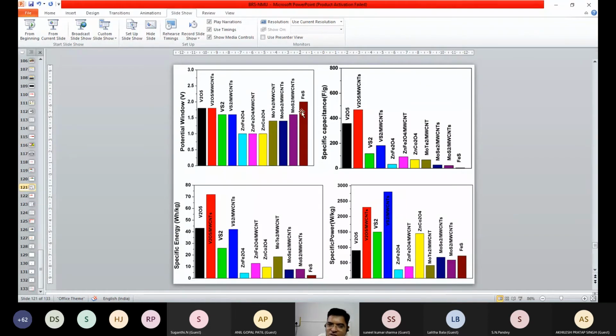But on the contrary, you can see that iron sulfide, although it has a very high value of potential window, has a very low value of specific power and specific energy, because this is a single material, right? And this material is dual, meaning what? One is pseudo and the other EDLC. That's why it is showing a very high value of specific energy.